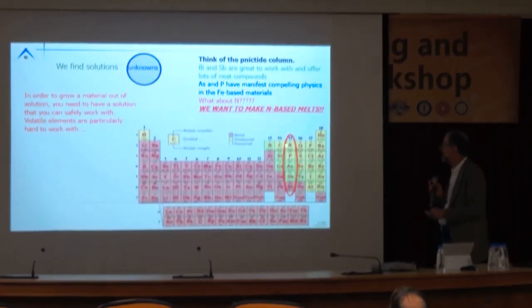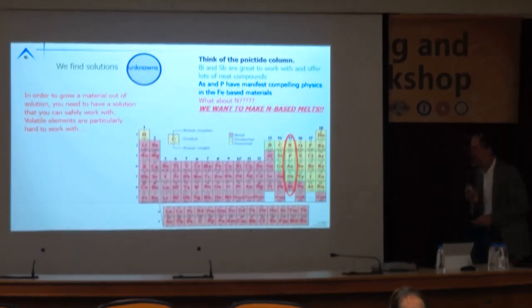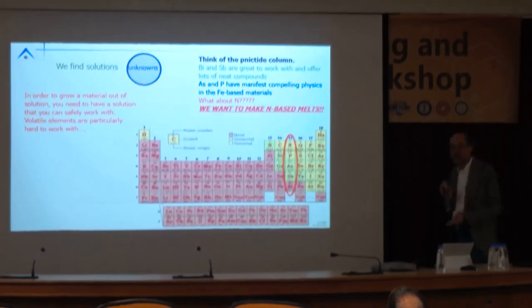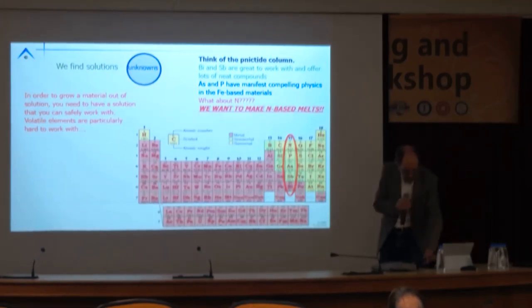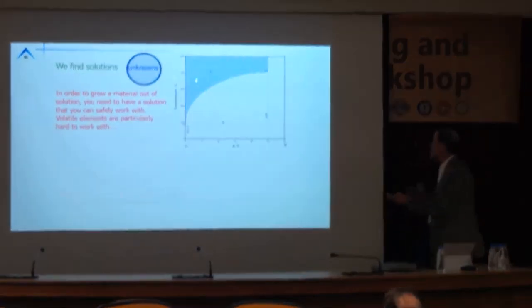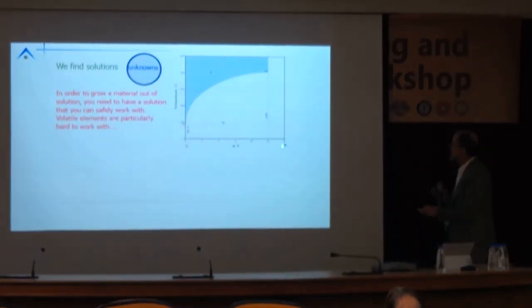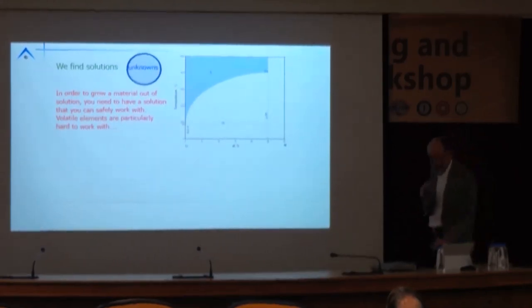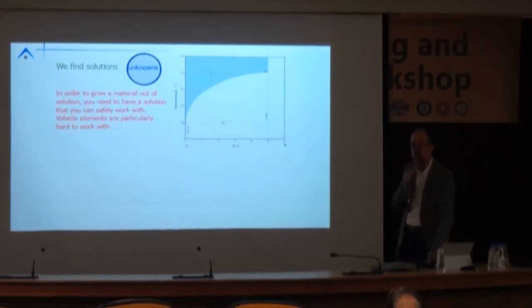As we move up this series, we're narrowing our bandwidth. It would be lovely to grow crystals with nitrogen. But getting nitrogen in solution is not easy. Okay? If I look at binary phase diagrams, though, lithium nitrogen shows that as we go from lithium to lithium 3 nitrogen, there's allegedly a liquid. It's not clear if there's a lot of vapor pressure over this, though, so we need to go in carefully because you might have explosions with molten lithium, which sort of are fun, although you might be less enthused during the day. But that, oh, someone likes lithium salts.